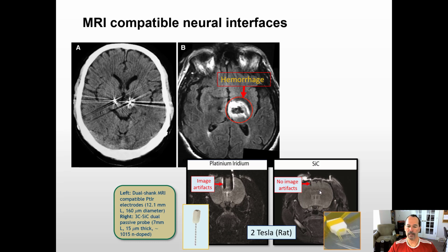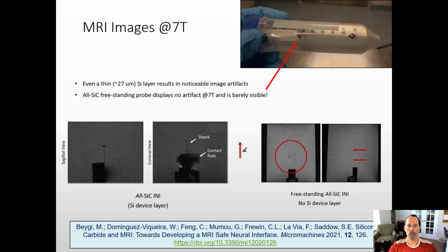So this gave us the idea to follow this further, and we have now done the experiments and a lot of simulations, and here we see our implant. In this case, there was a 27 micron thin device layer from the SOI on the backside of the implant. When we looked at both sagittal and coronal views in 7 Tesla MRI, we did actually see a little bit of artifacts at the tip, which was caused by the silicon on the backside.